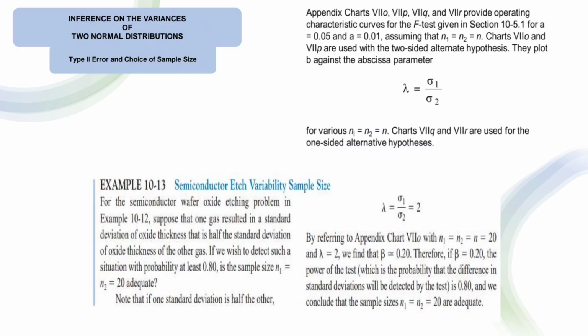Example 10-13, for the semiconductor wafer oxide etching problem in the previous example. Suppose that one gas resulted in a standard deviation of oxide thickness that is half the standard deviation of oxide thickness of the other gas. We wish to detect such a situation with probability at least 0.80. Is the sample size n1 equals n2 equals 20 adequate? By referring to chart 7O with n1 and n2 equal to 20 and lambda equal to 2, we find that beta is approximately 0.20. Therefore, beta is equal to 0.20. The power of the test, which is the probability that the difference in standard deviations will be detected by the test, is 0.80. And we conclude that the sample sizes n1 and n2 equal to 20 are adequate.